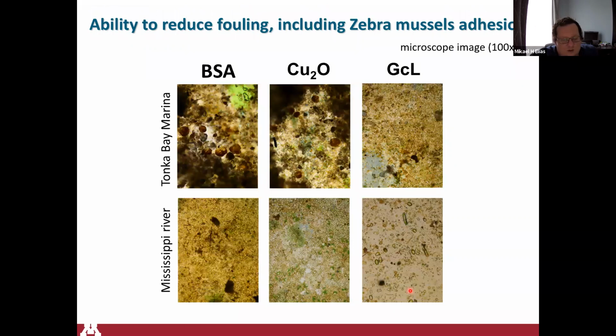If we look into more details, the advantage of using polycarbonate for sampling is that this material is transparent, and so we can do some imaging and actually study under the microscope to investigate what organisms are actually present. And so you can see here, in particular in the samples in Tonka Bay, you have the control with the inactive enzyme, you have the control with copper, and you have the treatment with our enzyme. You can see here that you have small mussels that are called veligers, and you have quite some here, you have quite some here, and you have none here. All right, so this is again very encouraging for us.